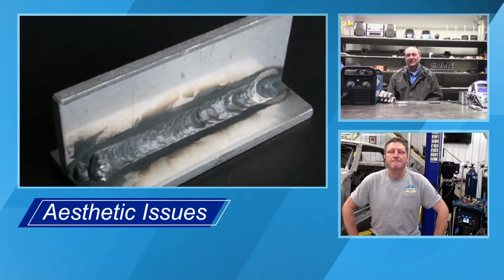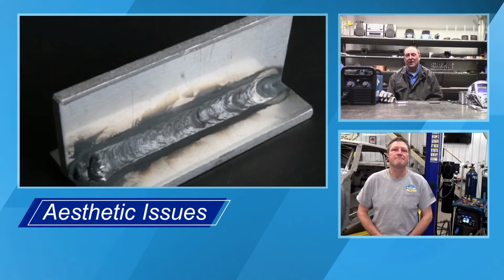Andy, another thing, you could go back to that image of the weld. Something else I want to talk about, if you look on the right side of that image, that's where the arc ended, or the stop, or the crater. Something you hear about with aluminum is that at the very end, that crater is actually below the surface of the face of the weld. So sometimes with aluminum, you'll have what they call crater cracking. Let's say you're repairing a trailer, it's going down the road, it's flexing all the time. That vibration or flexing could start in that dimple of the crater and start propagating back up through the weld, cracking the weld.